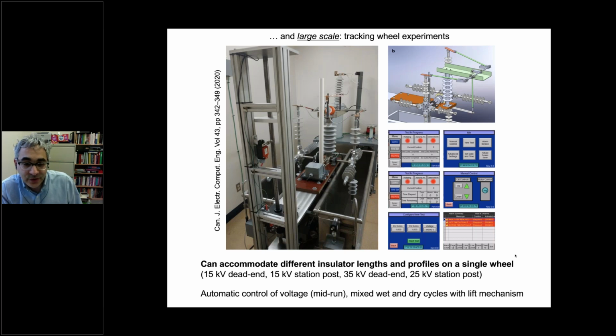First of all, you can see that there's two tanks here in the photo. One of the tanks can be filled with, let's say, sodium chloride solution, and the other tank can be filled with magnesium chloride. We can look at different de-icing salts. And then you can see two wheels or two rotors, and on each side, we can mount up to four insulators. One of the things that's special about our design is that we can accommodate insulators of different lengths and different profiles, dead end, station posts, different types of configurations, all on the single wheel. So we can mix and match lengths and sizes on one side.